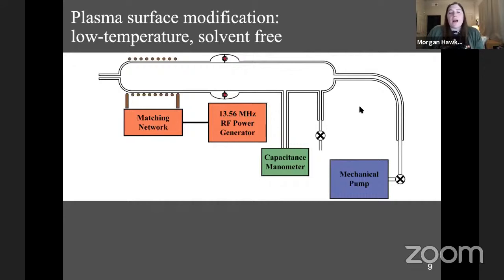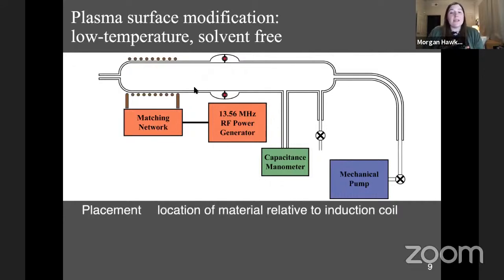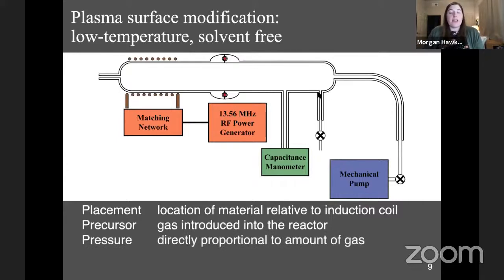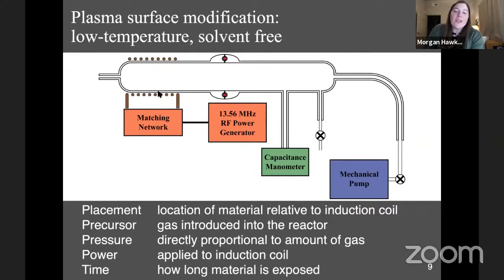So as I alluded to, plasma treatment is highly customizable. For example, we can change where we place the substrate relative to the induction coil. You saw in the previous slide that the plasma glow is very intense in this region closest to the coil and tends to be more diffuse further away. So that can have important implications on the modification outcome. We can also change the precursor itself, what that gas is that we're introducing. We can adjust the pressure by changing the amount of gas added to the reactor. And we can change the applied power, so applying a higher or lower radio frequency power, higher or lower amplitude, I should specify that. And then lastly, the time, so how long the material is exposed to the plasma. That has important implications as well in terms of the resulting modification.